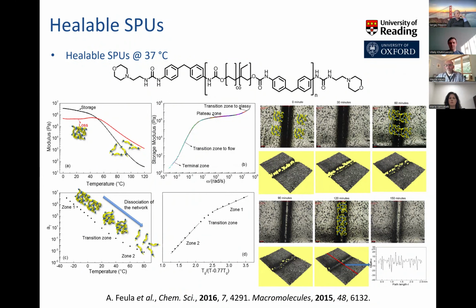And so the way that we do that is that we take our film, we cut it, we put the two ends in close proximity, and then we thermally anneal them, and we study that by microscopy, and those are the images that we've shown you there.